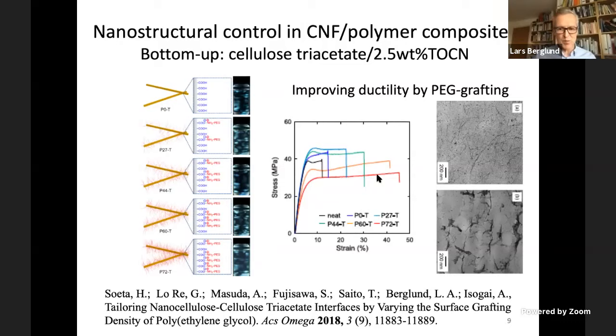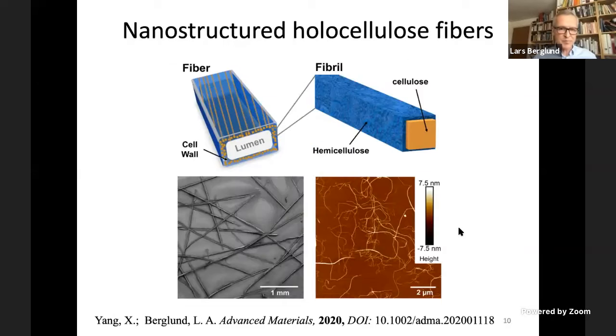So this is very well-controlled material, although from the point of view, if you compare with native structures, this is TEM image in the lower right corner here, you see there are still PEG-rich blobs here. So it's not that easy, and it's very, very tedious to control the structure. So for this reason, it's really interesting to try to use the native structure and its existing nanostructure.